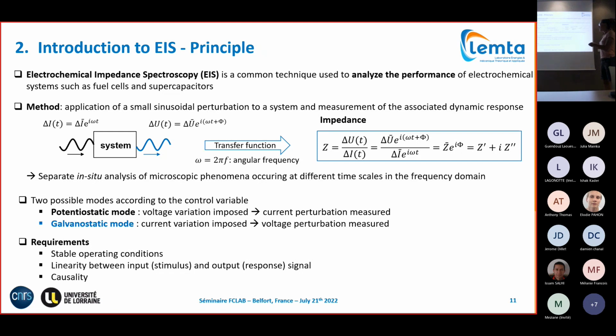According to the control variable, you have two different modes of EIS. One we call potentiostatic mode, when you apply voltage variation and you have a current perturbation, and you call it galvanostatic mode if you apply current variation and you have the associated voltage perturbation. In our case, we apply galvanostatic mode because it's easier for fuel cells, and potentiostatic mode for supercapacitors.